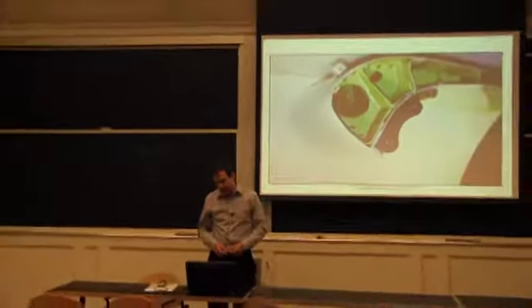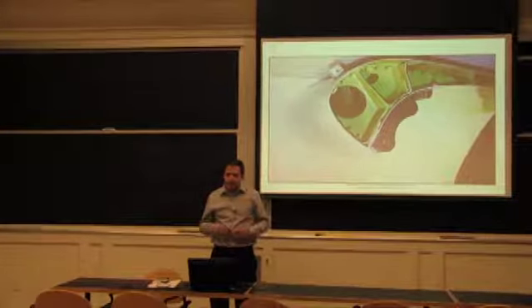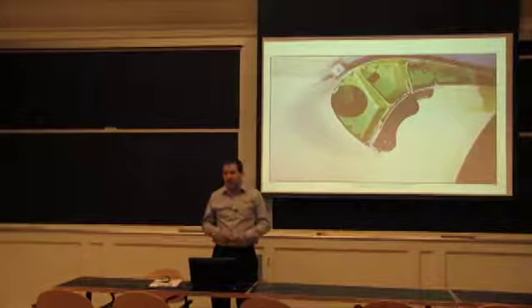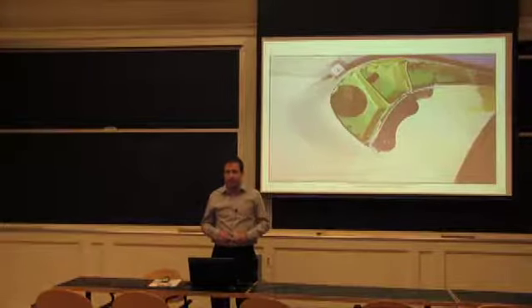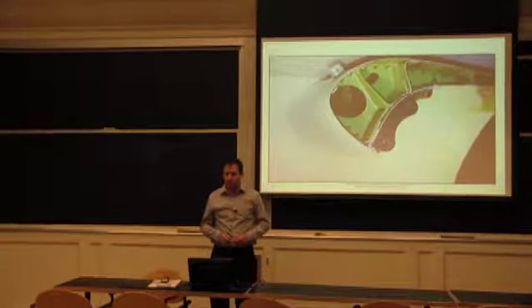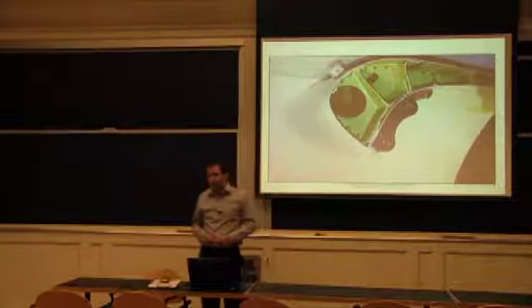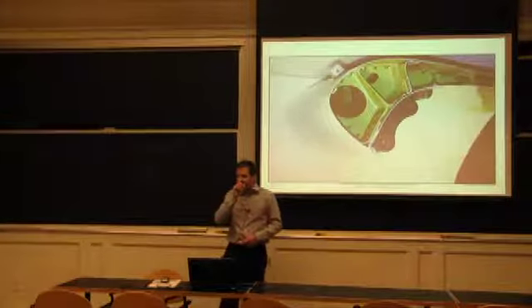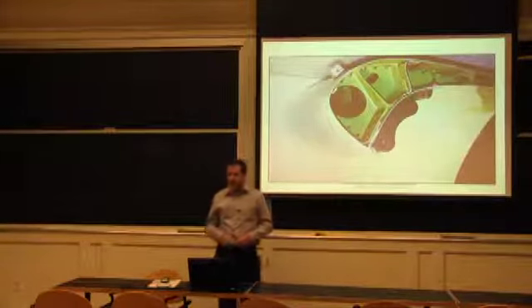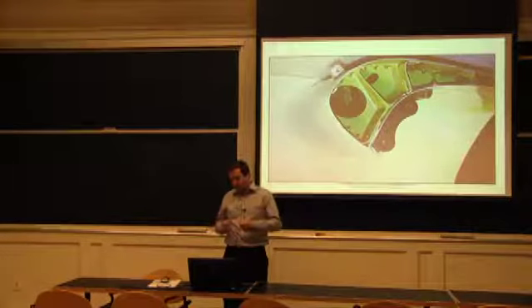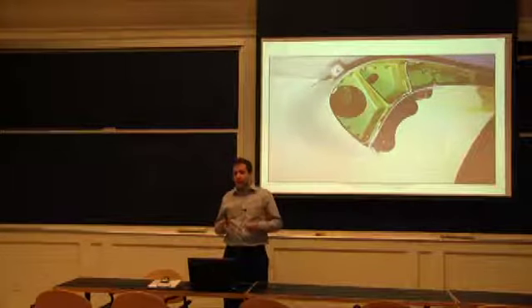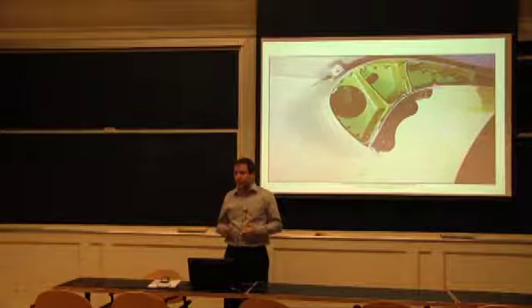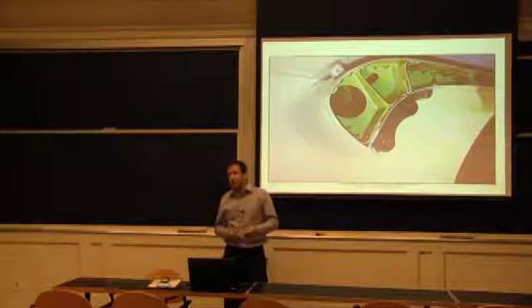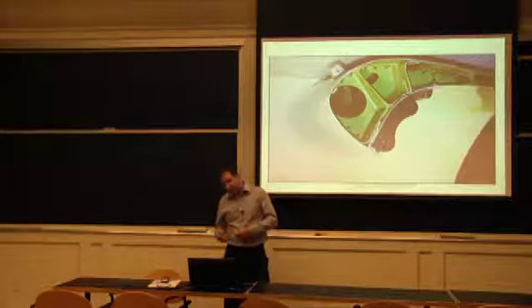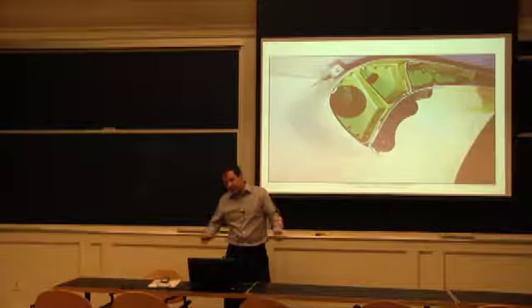So we had to run all the standard tests. We had some tensile tests to get the yield and the ultimate strength. We had fracture toughness tests. We talked about that KC in the last class. Then we had some fatigue tests where you cycle a sample that has a crack in it, and you look at how fast it's growing over time. So we had all sorts of tests: fatigue with a notch in it, without a notch in it. We had all that data.